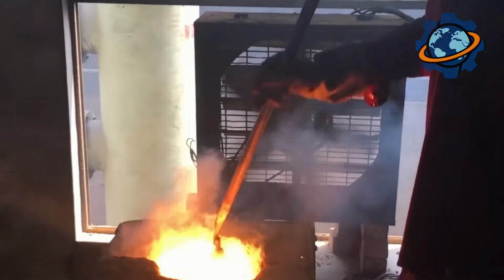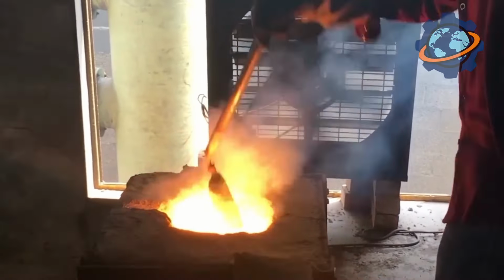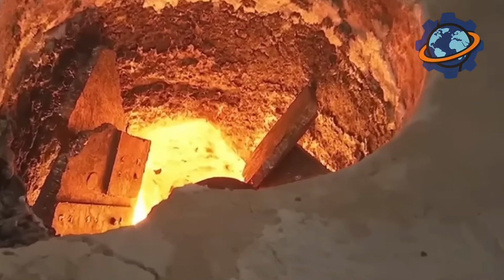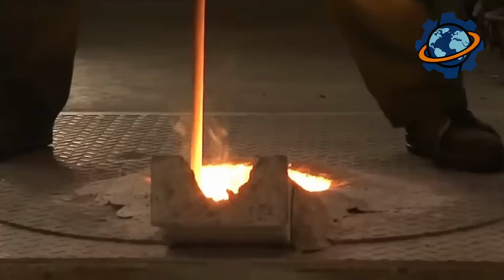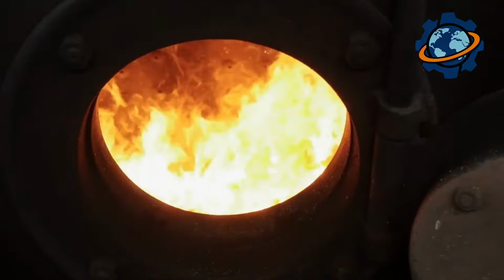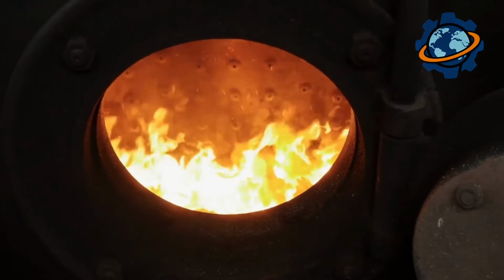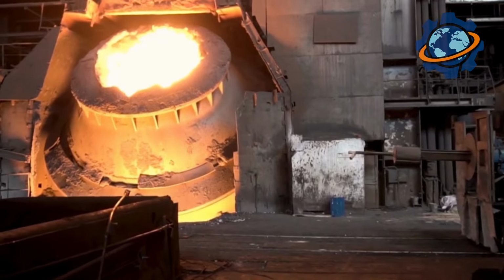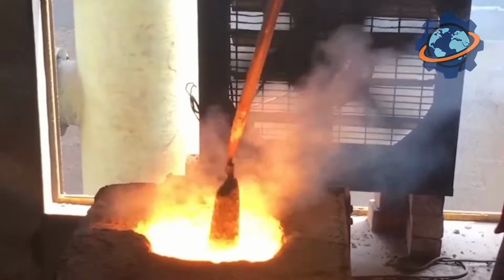Induction heating ensures rapid and uniform melting of all components, creating a homogeneous melt. The melting temperature in such a furnace can reach over 2,700 degrees Fahrenheit. After achieving a complete melt and homogenization of the alloy, the stage of rapid cooling, known as the strip casting method, begins. This is a key moment for forming the optimal microstructure.